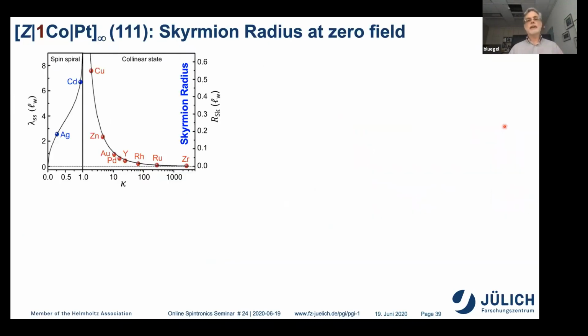And now we put everything together. We have the A, the D, the K, and you see each element on this plot. So we have two elements, cadmium and silver. They form one-dimensional spiral states as ground state. At zero field, you cannot form skyrmions. You need a large field to turn them into skyrmions. Whereas for those elements, you get skyrmions at zero field. And you see, for example, the radius can vary in these domain wall radii from 0.5 to basically 0.